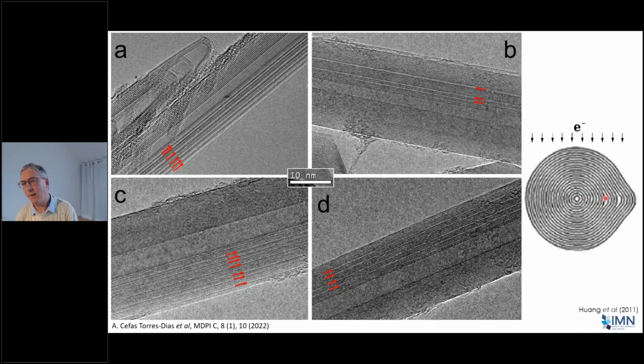If you take a large system, then the bulges tend to line up one with the other because it makes more sense mechanically. So you get all these extra little gaps on the same side of the nanotube each time. And this is actually very common in really nice clean arc-discharge nanotubes. So if anybody tells you that a multi-walled nanotube is cylinders inside cylinders, the actual answer is not quite.